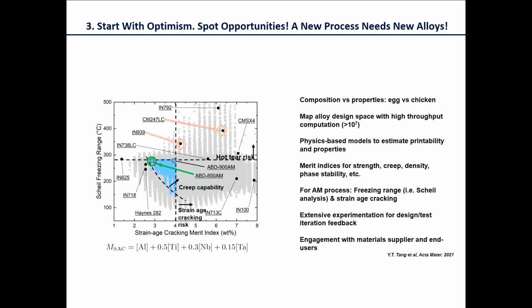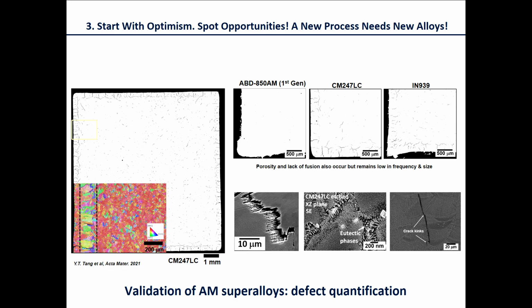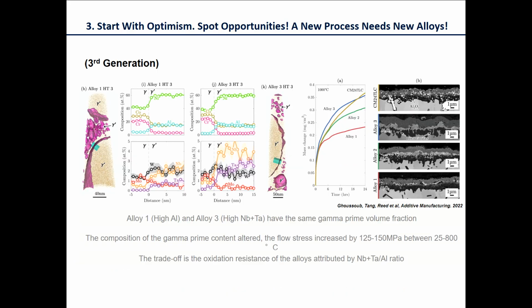And Professor Tang did this work for his PhD and postdoctoral work. You can see from these slides, these are typical coupons for additive manufacturing material. This is the first generation alloy that we designed. And you can see here, right first time with these concepts, we were able to design something that actually performs better under identical tests than the existing alloys, which do crack under these circumstances. So this gave us great confidence in what we were doing with regard to designing new kinds of materials.